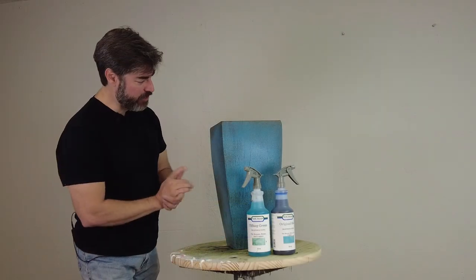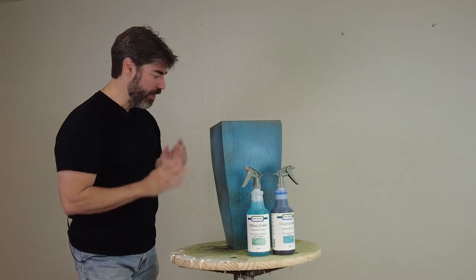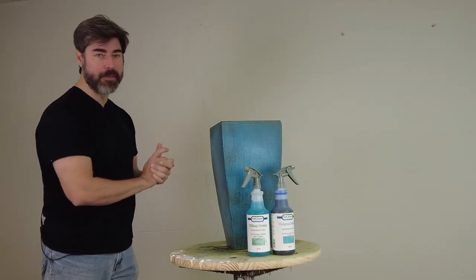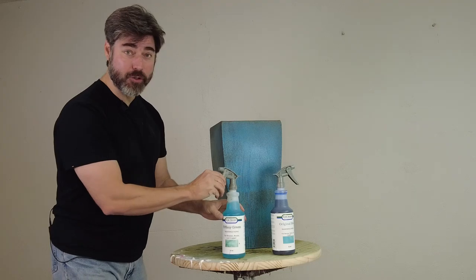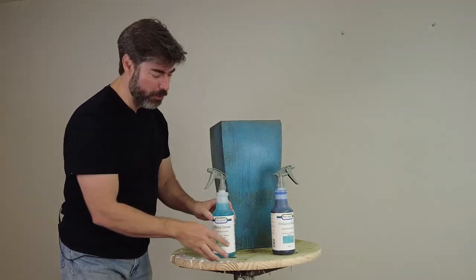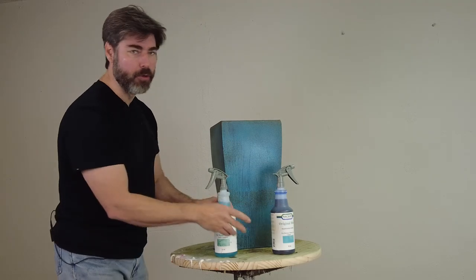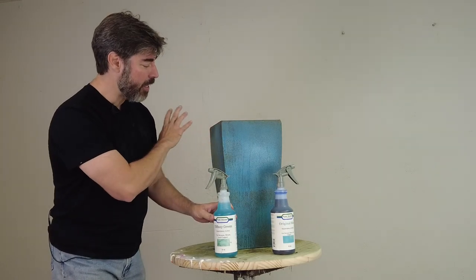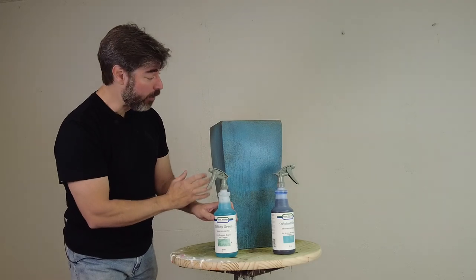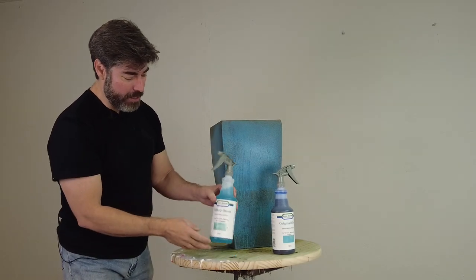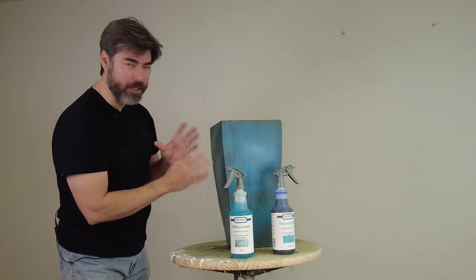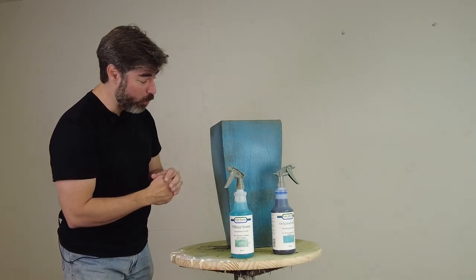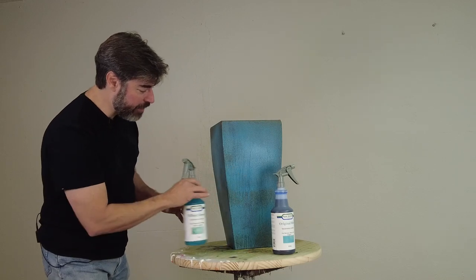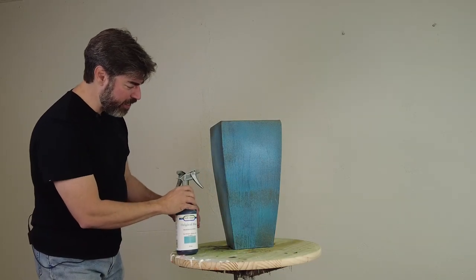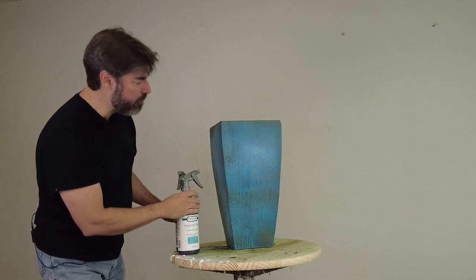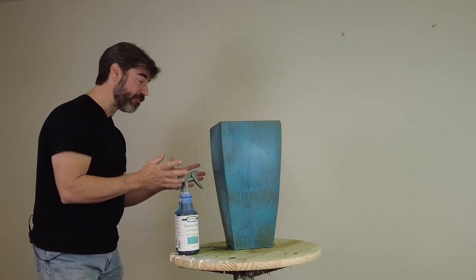Okay, so this is about 20 minutes later or so, and we have a really nice blue-green patina forming. Obviously, we didn't have to use both of these. I could just use just original blue or just the Tiffany green. Original blue will do just that. It's gonna oxidize copper or any kind of copper alloy to blue, whereas the Tiffany green gets more of a green, but I really like the two of them together. They get a nice kind of turquoise look, and we're getting a nice reaction. This will probably take another hour for it to fully develop.